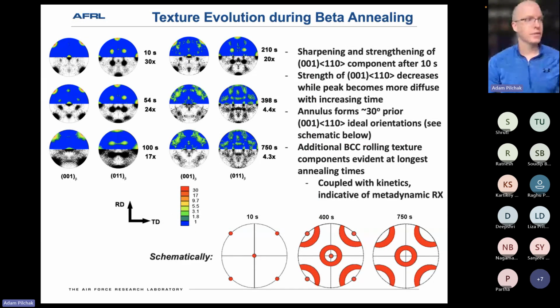All right. A lot of the remainder of the story has to do with crystallographic texture, and so I'm going to show some pole figures and some orientation distribution functions along the way. These are some composite pole figures that we produced, where the top half is showing the classical representation of intensity, right? So you run the spherical harmonics and can determine what's the probability of finding grains in a specific orientation. On the bottom here, these are discrete pole figure plots where each individual pixel in the EBSD data set contributes to a set of points corresponding to that plane normal. So in this case, for (001), each individual pixel in the data set would produce three 100 poles on this pole figure.